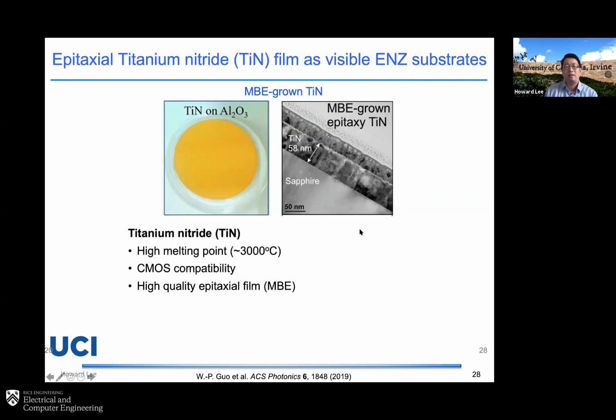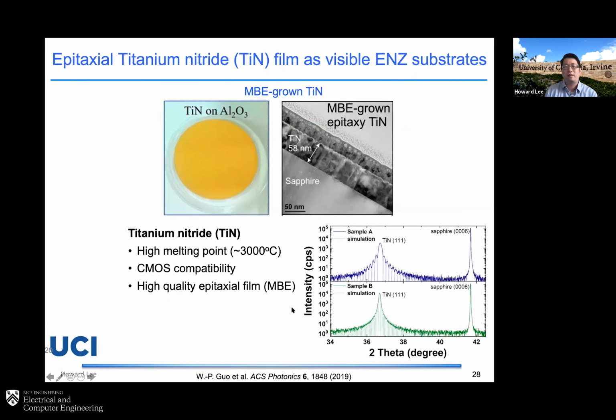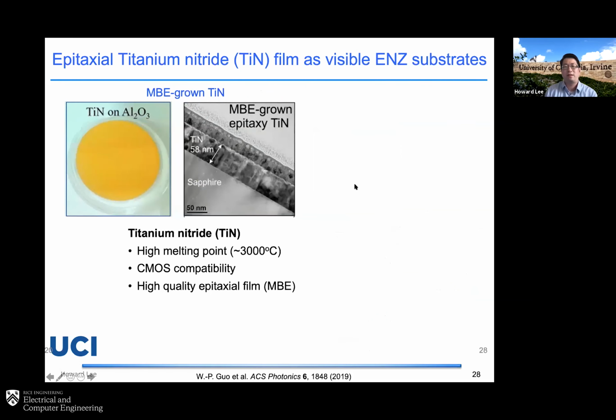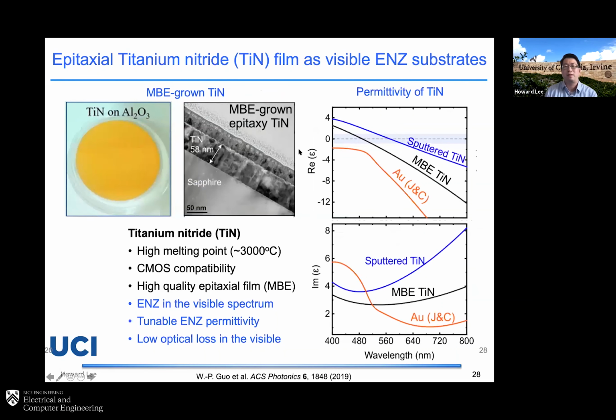Other than that, the good thing is that again you can make a single crystal with a really large area thin film like this here. And you can have a visible ENZ wavelength on this kind of titanium nitride material. For example, if you look at the permittivity here, for the MBE-grown titanium nitride the ENZ wavelength is around 500 nanometer, and you can also sputter the titanium nitride and have an ENZ around 560 nanometer.